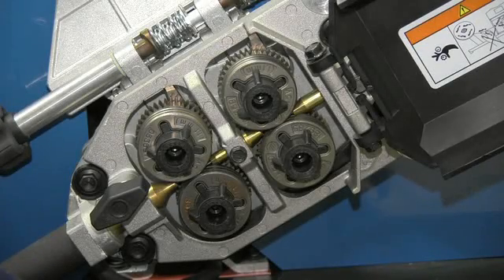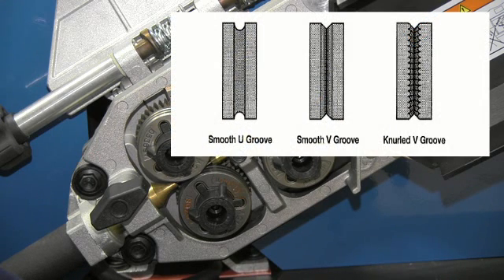Another item to check that's really simple to check is the drive rolls. The drive rolls should be the same size as the wire that you're using. If you're using 045 wire, then you need to be using 045 drive rolls. If you're using solid wire, the U-groove drive rolls are recommended. If you're using a cored wire, flux cored or metal cored, most of the time a V-knurled groove is recommended. And for aluminum, you want to use a U-groove drive roll. So make sure that the proper drive rolls are installed.